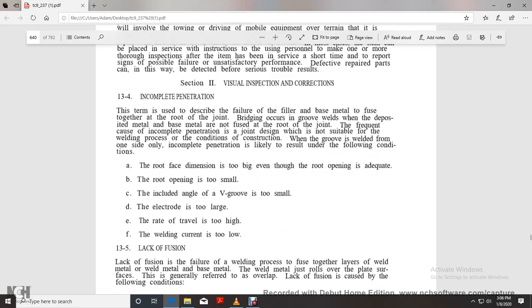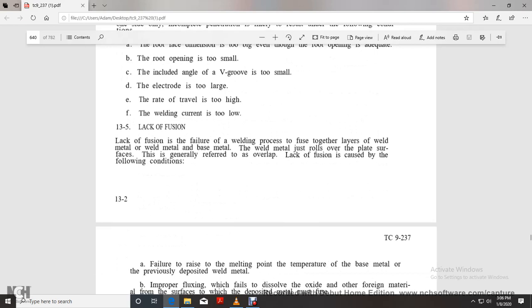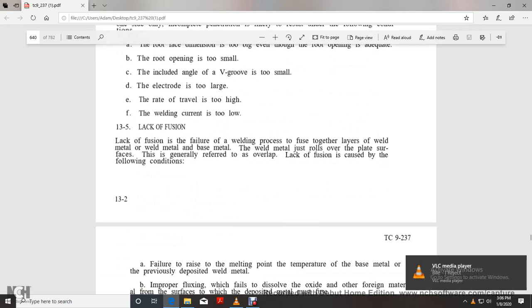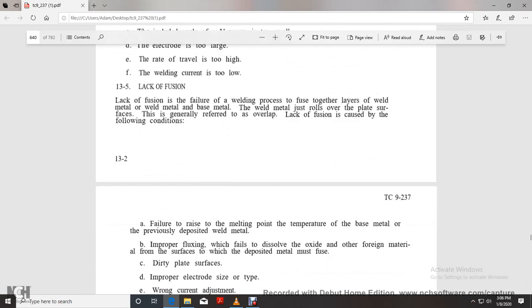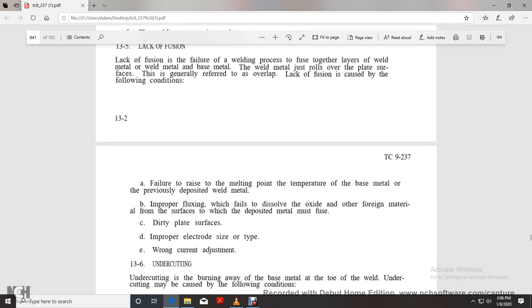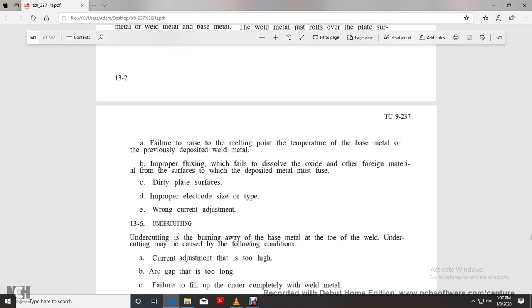Lack of fusion. Lack of fusion is the failure of the welding process to fuse together all layers of the weld, the weld metal with the base metal, where the weld metal just rolls over the plate surface. The overlap and lack of fusion are caused by the following conditions. Failure to raise the base metal to its melting point with the previously deposited weld material. Improper fluxing, which fails to dissolve the oxide or other foreign material from the surface of the deposited metal. Dirty surface, improper electrode type, wrong current adjustment.